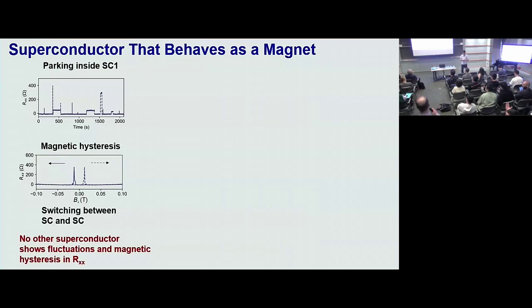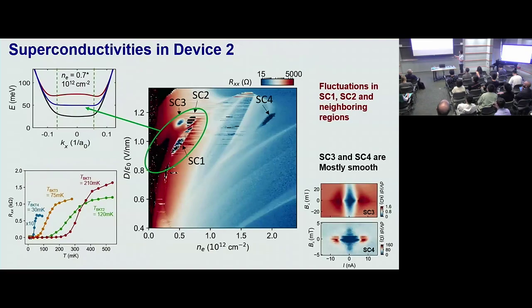We have time for a couple more questions. Thank you for the very interesting talk. Do the other superconducting domes show a similar magnetic hysteresis? You had four of them, two of which had this unconventional character, two didn't. Is this magnetic hysteresis similar for all of them or not? It's probably similar for SC1 and SC2, but not 3 and 4. Sorry, which were those two? 1 and 2 are the jumpy ones. But 3 and 4 did not have it. No, 3 and 4 just look like, especially 4, you see it's at some phase boundary, and that's probably similar to seeing bilayer and trilayers where maybe isospin fluctuation is mediating superconductivity. Gotcha. Thank you.